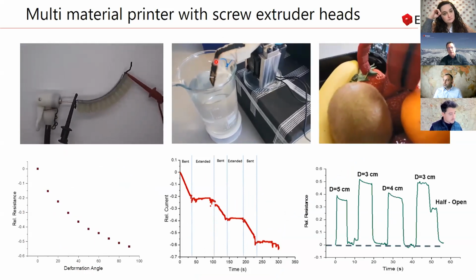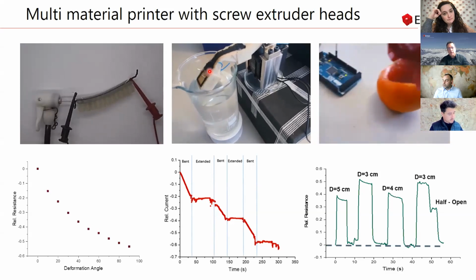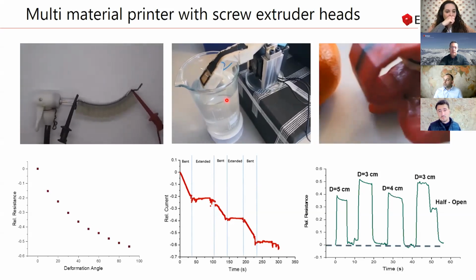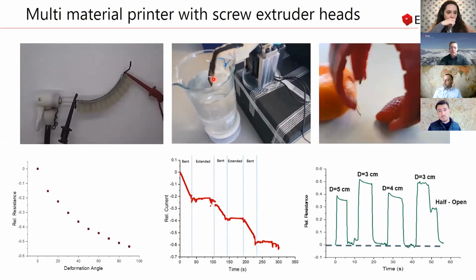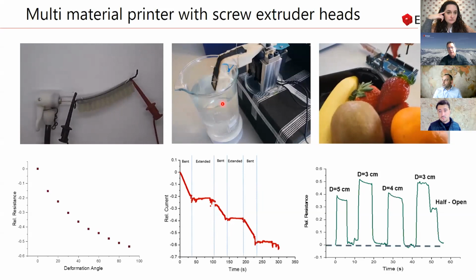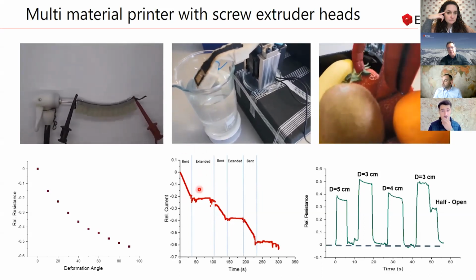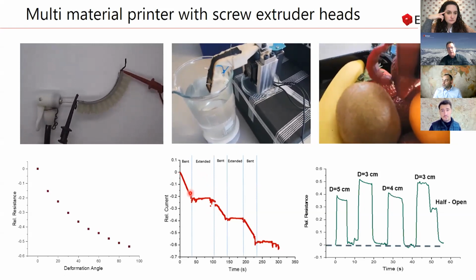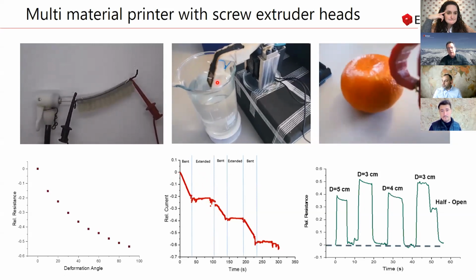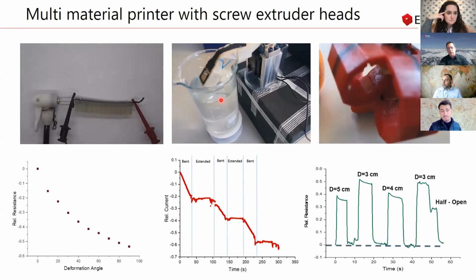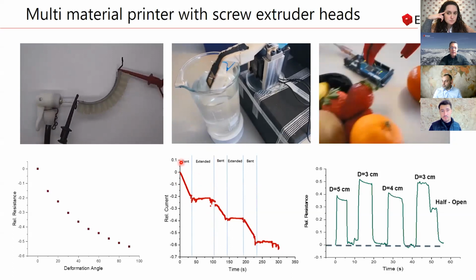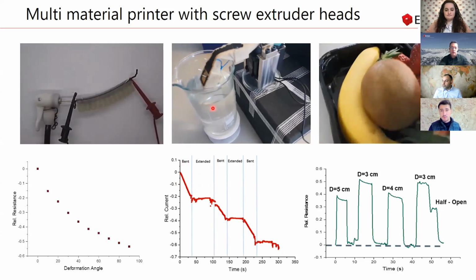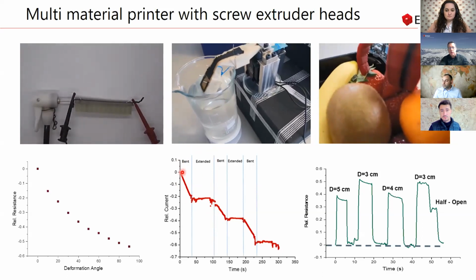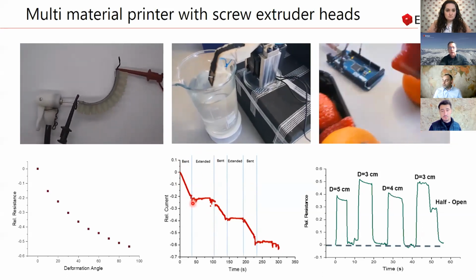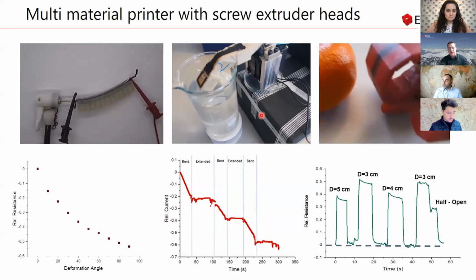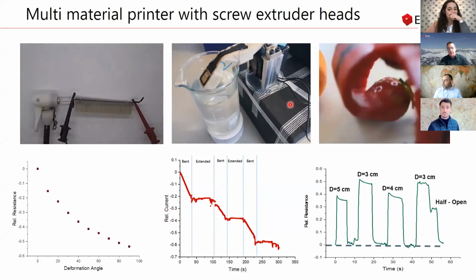The other possibility is that you can measure, for example, here the solvent. So that means you measure here the vapor of the solvent, which is above the liquid. And you see when we bend it and when we extend it, then we bend it and extend it, you see that then the current always goes down because the concentration above this liquid increases over the time. But you can really nicely see that when we always go close to the surface of the liquid, we always have a huge decrease of the current, which means we can detect nicely the chemical species inside.